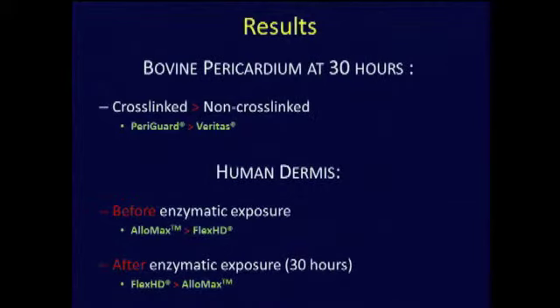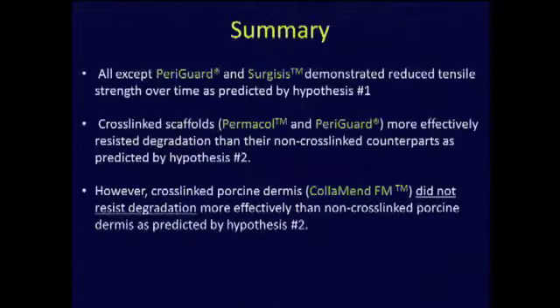In terms of human dermis, there was one interesting finding, and that is before enzymatic exposure, one of the allografts had an increased tensile strength, increased tensile strain, and decreased modulus. But after enzymatic exposure, we actually saw a reverse in the mechanical properties of those materials, essentially meaning that the processing, which is proprietary for the company, has alteration in the effect of that material after enzymatic degradation.